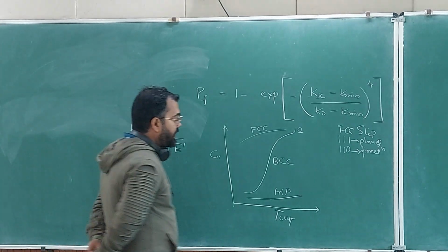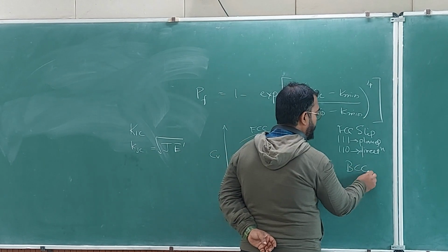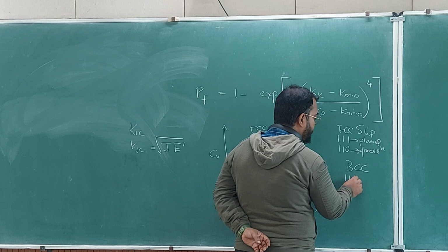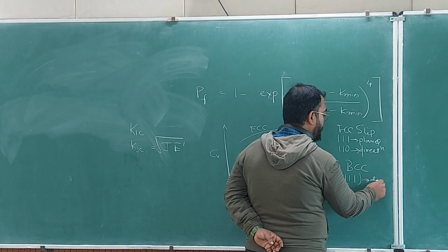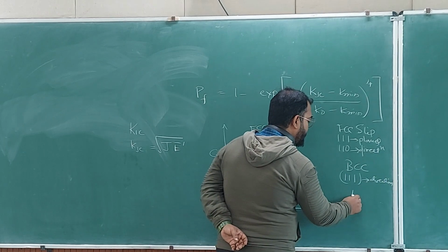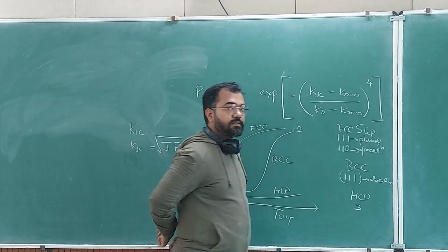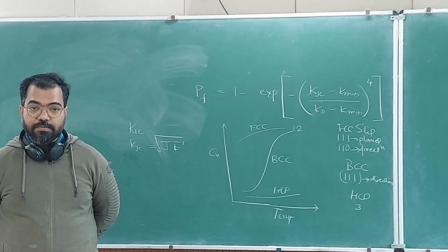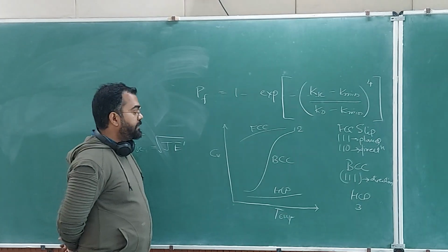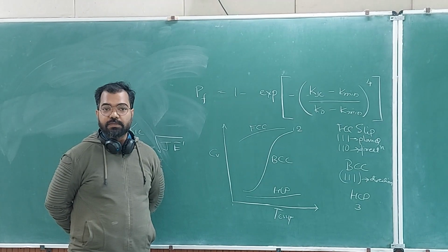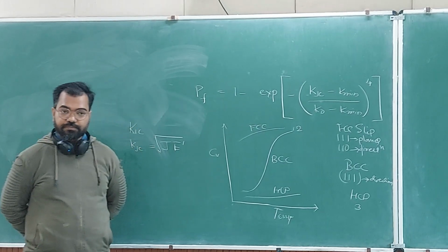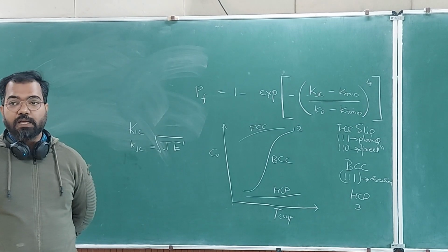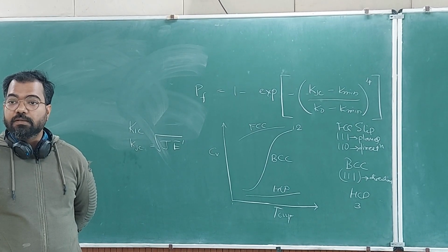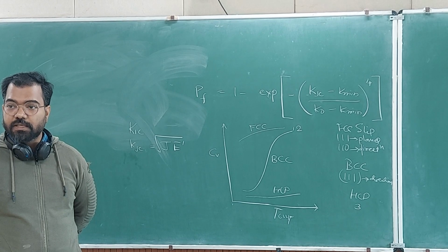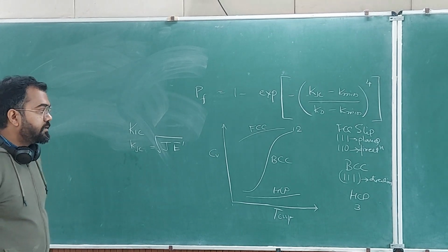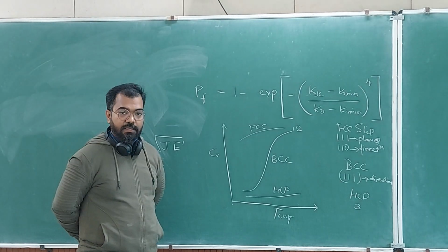In BCC, you have 48 slip systems. Okay, and there the slip plane changes, slip direction is 111. And in HCP, you have 3 or less than 3, sometimes 2, sometimes 1 slip system. So this is why HCP will not give you that much toughness. So magnesium will not give you that much toughness. Zirconium will not give you that much toughness. And all FCC, aluminum, what other? Nickel is FCC. So these materials will give you very high ductility.